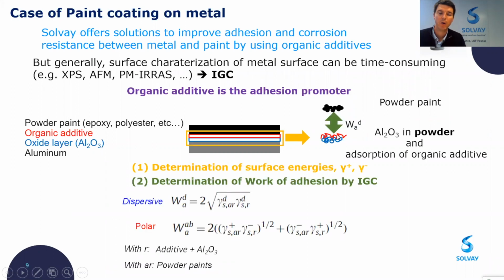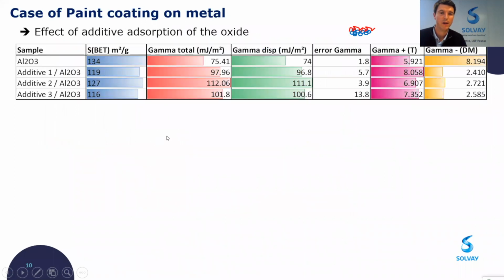And we can also try to estimate the work of adhesion by using these two equations with a dispersive component here and a polar component. And we can try to predict this adhesion with this equation. So here is the result, as you can see here on this slide.